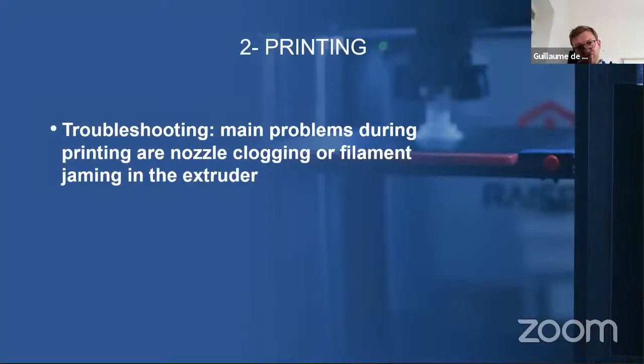So what are the main problems you may have during printing? The two really main problems are nozzle clogging and some filament jamming in the extruder. Nozzle clogging can happen, but usually, really, if the printing parameters are good, if you're careful about the first layer being laid correctly, it's pretty rare. And when it happens, well, you just have to unclog. There's nothing else to do. Using a small needle or whatever, you need to unclog the nozzle.